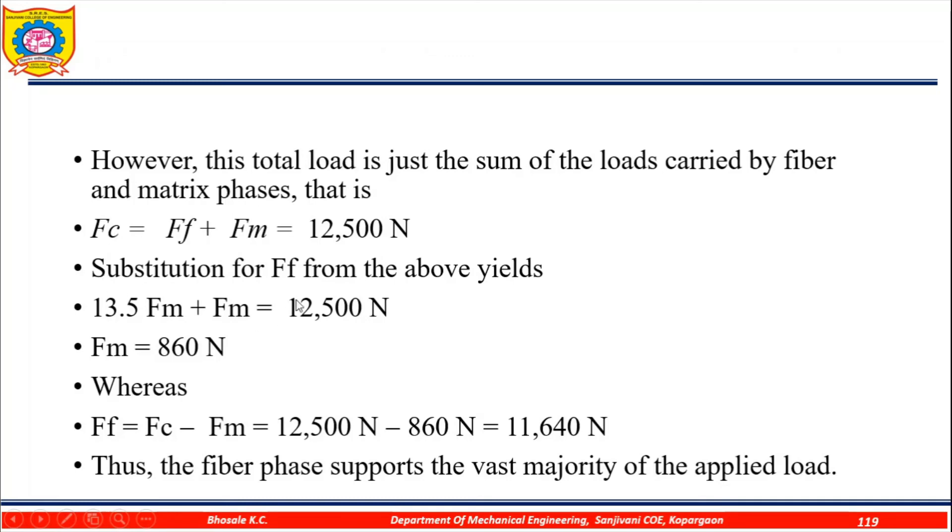Substitution for F_f from the above yields, we are getting F_m equals 860 newton, whereas F_f equals 11,640 newton. Thus, the fiber phase supports the vast majority of the applied load.